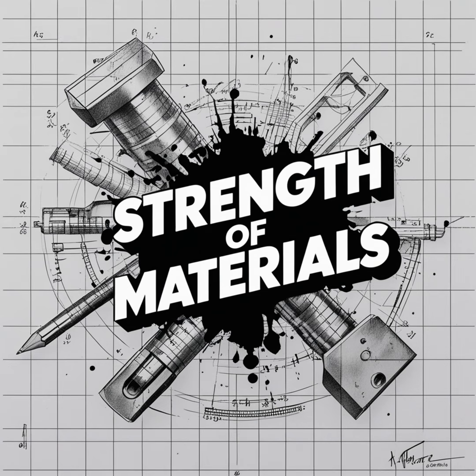Okay, one final concept here to wrap up the physics. If the metal is stretching so much under this large-scale yielding, if the J integral is working so hard, the crack itself isn't just a microscopic, mathematically sharp line anymore, right? It must physically deform. Absolutely. The mathematical concept of a sharp crack tip breaks down in reality. And this brings us to a physical measurement called CTOD, the crack tip opening displacement. Crack tip opening displacement. Yeah. Because of the massive plastic deformation happening at the tip, the crack literally blunts. Before the crack actually advances forward and tears new metal, the tip stretches and opens up into a U shape. So you can physically measure how far the jaws of the crack stretch open before they snap.